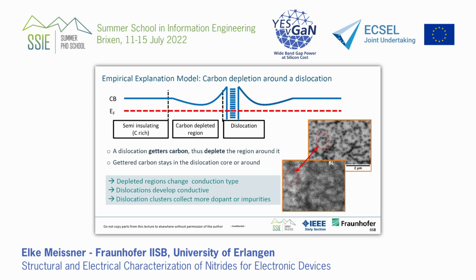And you see that there are areas which emit in blue light, in the blue luminescence, and which do not emit. So what you find from this, if you put all together, is that dislocations gather the carbon and deplete the region around the carbon. So what we found is that there are dislocations in such regions where we don't see the blue luminescence. So at the middle there is a dislocation, and it grabs the carbon. So you have a region around the dislocation where the carbon is depleted. And this is the problem for